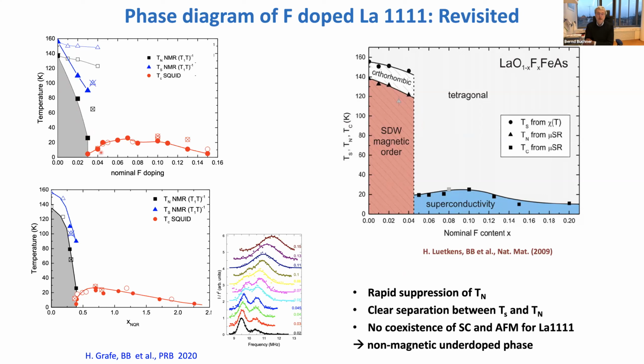And what we still have is that there is no coexistence between superconductivity and magnetism. So you have this well-separated region, and you end up with a region of so-called underdoped compounds where TC increases, similar to what we know from some of the cuprates. So that's very similar to the first thing. We also managed to get, let's say, an internal standard. The main problem is just to measure the electronic doping, and this you can do via NMR. If you want to know more on that, you can have a look at this paper where we describe that. And you can even take all the literature data, put it on the same phase diagram, and then all the things fit together. So that's the phase diagram which we know for these compounds.